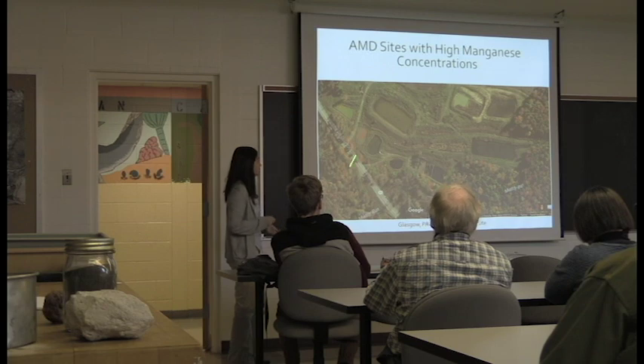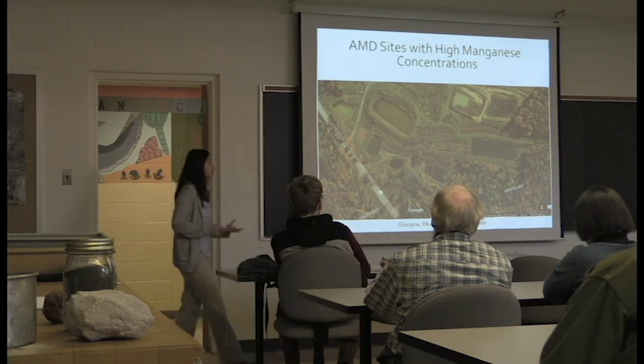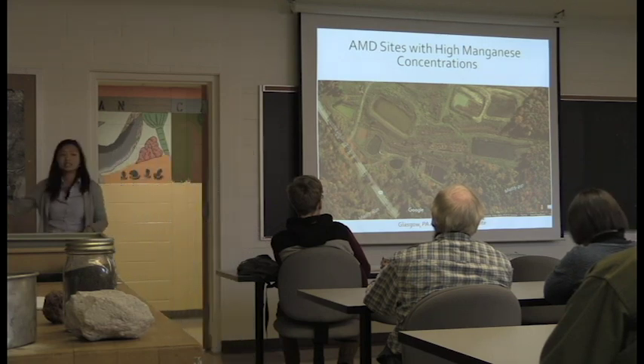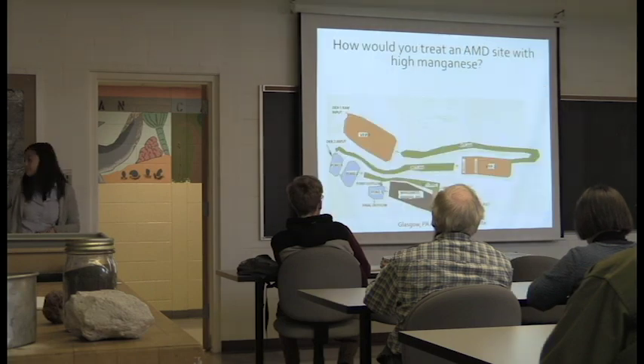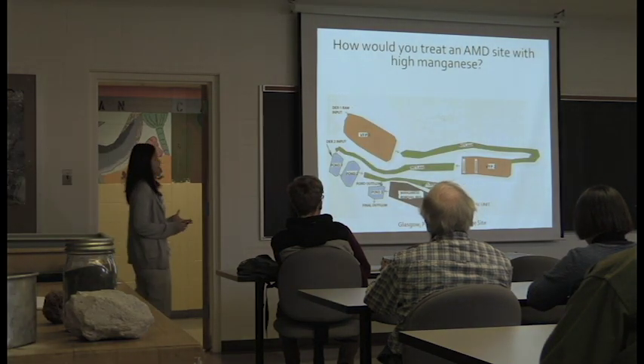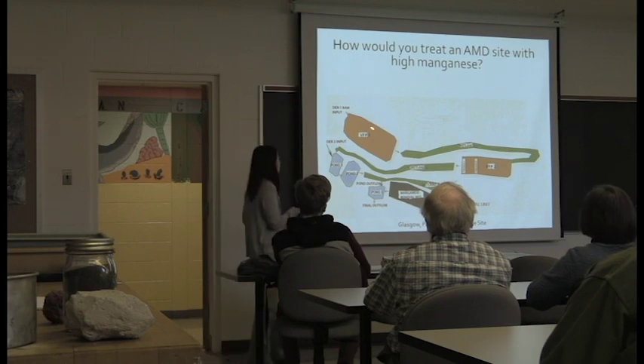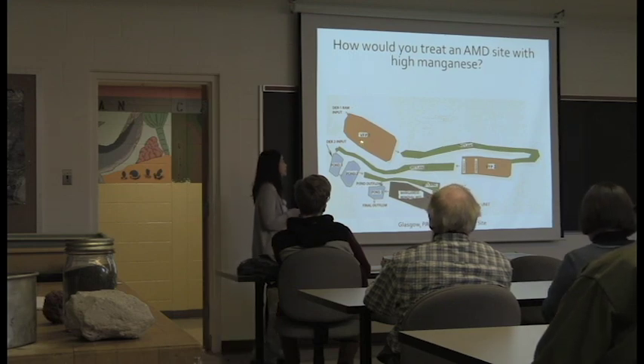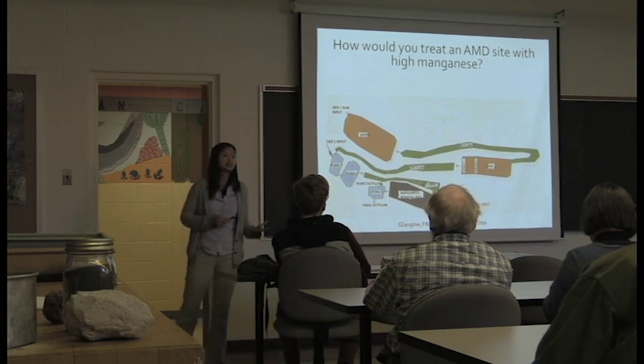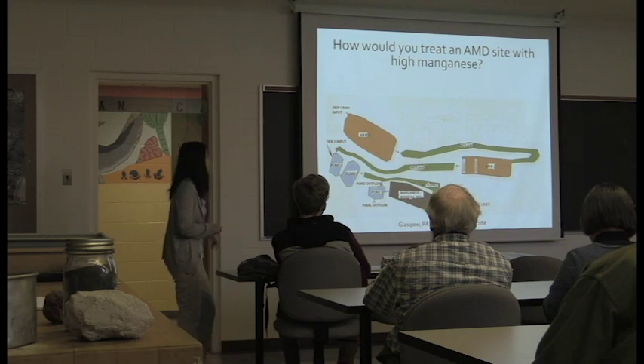And this is one of our sites in Glasgow, Pennsylvania. These ponds here are all part of this passive treatment system that they've built in this area to remediate the acid mine drainage. This is a map of what that passive treatment system looks like. First you start with the vertical flow pond, and so you're treating for sulfate and acidity there. Then you move down to a wetland where you treat for sulfate, and then back to another vertical flow pond, and then another wetland. Then these are settling ponds where we're letting iron oxides settle out of the system. And then we go back to a wetland.